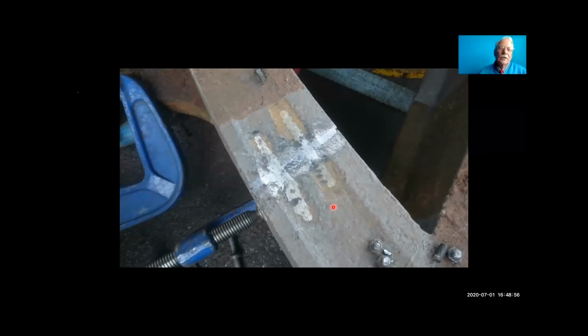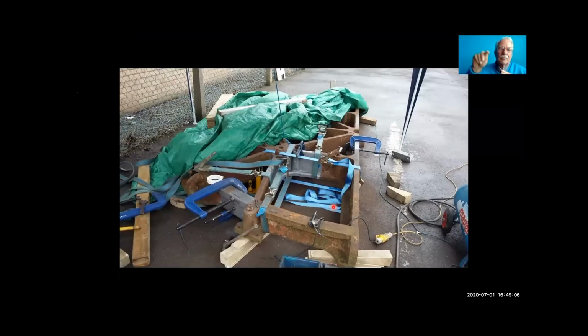If you drill a hole at the end of the crack, that reduces the stress raising characteristic of the crack. It tends to stop the crack propagating, but it won't strengthen it. Usually the cracks are very fine, unless they've completely broken apart.